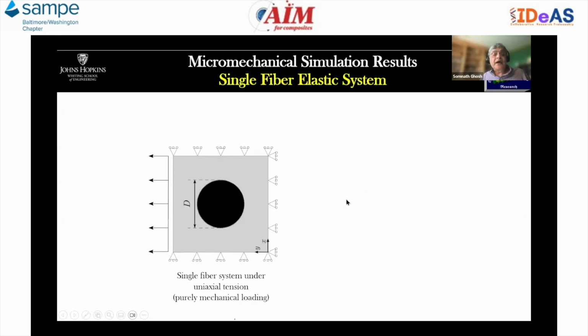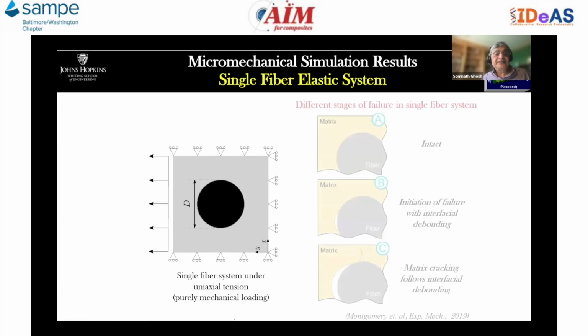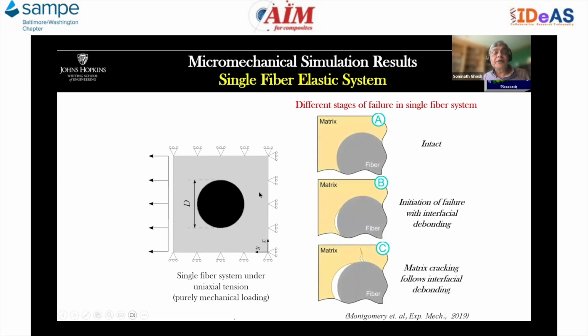Now, I want to emphasize that by doing a cohesive interface modeling of the phase field, we are able to reproduce or replicate experimental observations where, for a model like this, this basically consists of one fiber here. It's constrained like this, and we are applying a loading. This is just a mechanical loading. Experiments here have shown, just a minute.